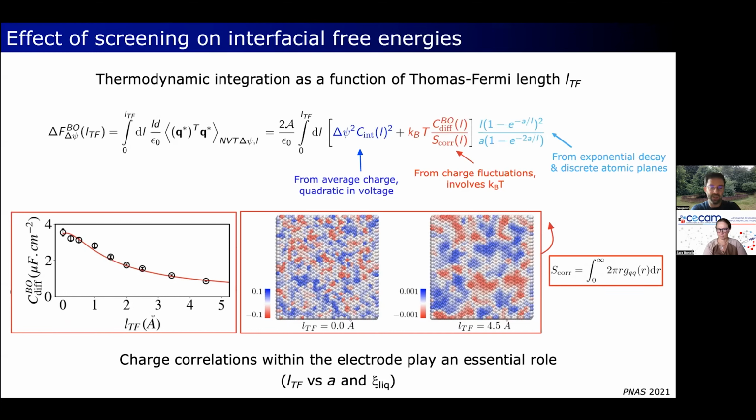So if I understand correctly, you're going to freeze the charge distribution, which is not homogeneous. It would look like one of the snapshots here. So in that case, you are really templating the structure of the electrolyte by the charge distribution inside the metal. So probably the configurations that the electrolyte will explore will be strongly biased toward configurations corresponding to the charge distribution. Whereas in the constant potential, you would explore basically all possible configurations that are compatible with the constant potential constraint. I don't know if that makes sense.